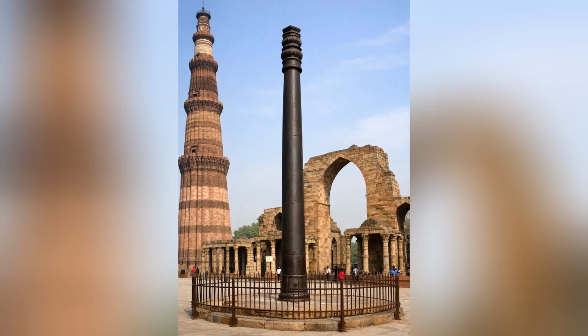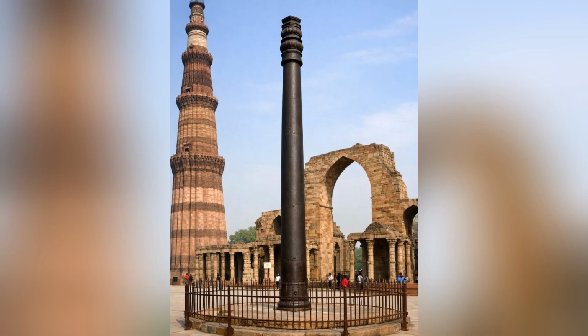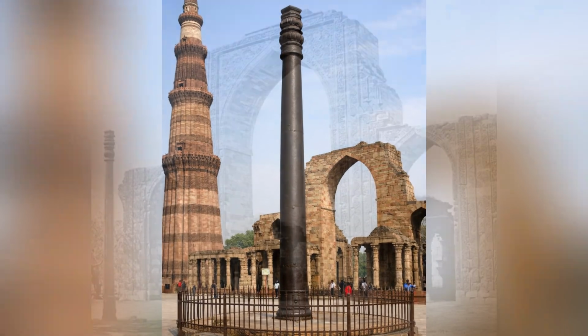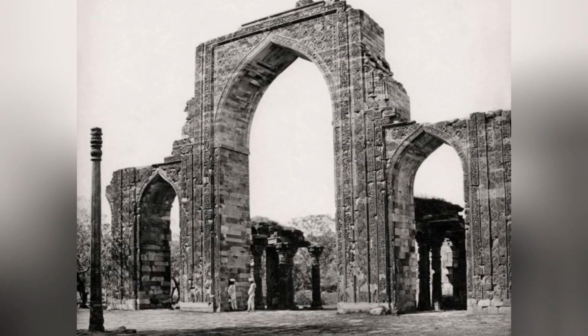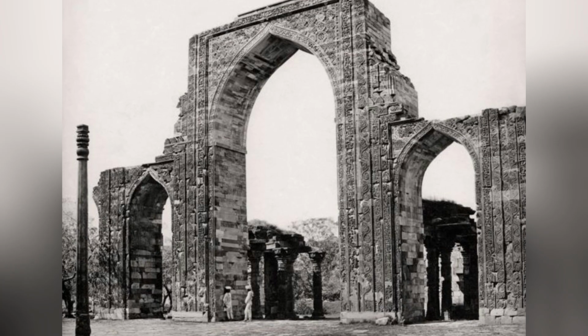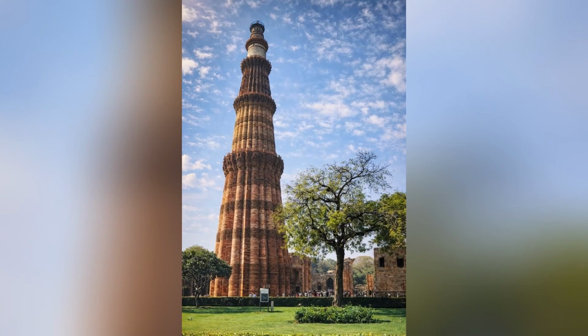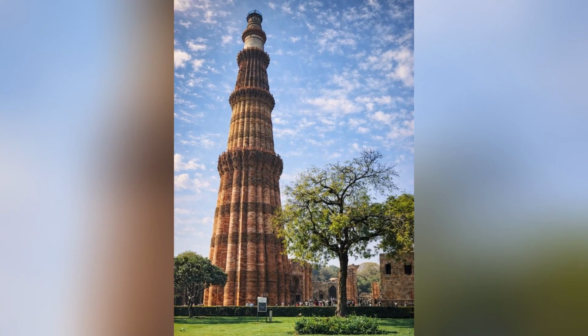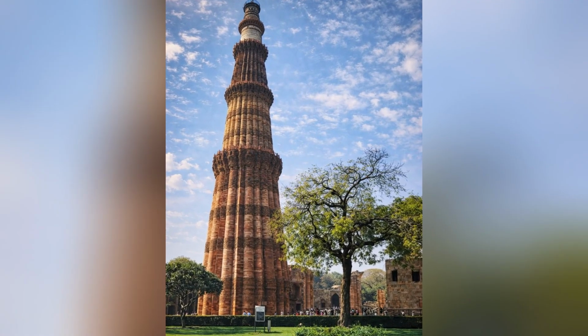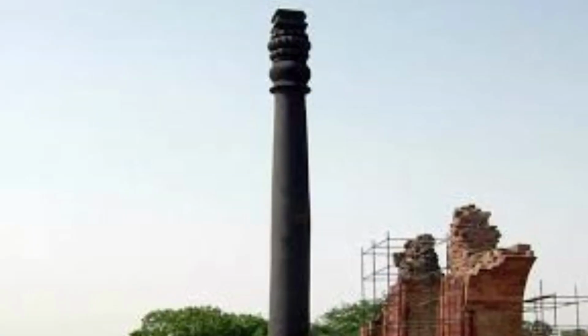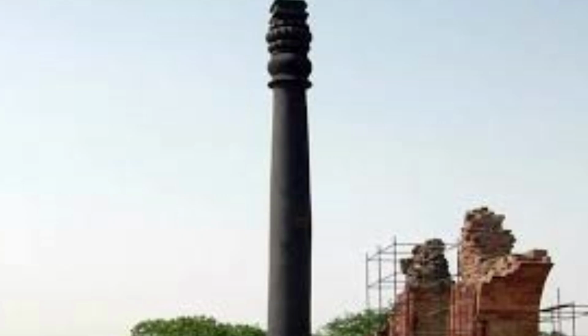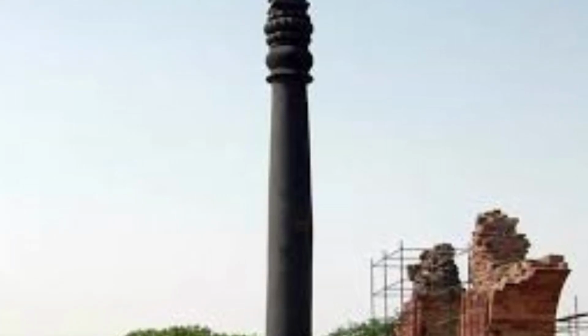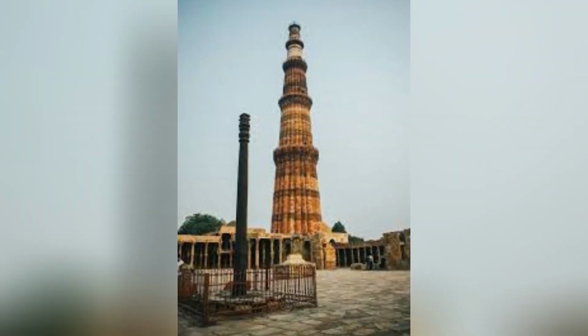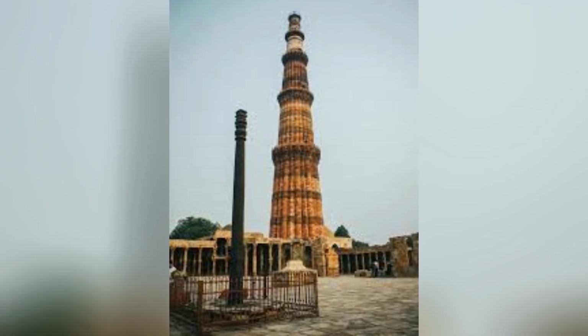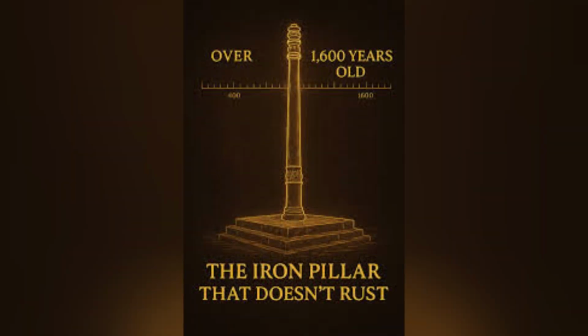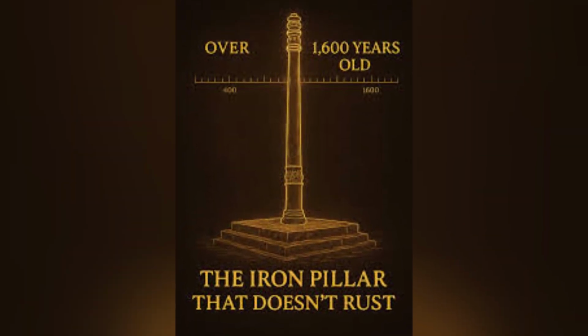The formation of the misawite film was a direct consequence of the high phosphorus content of the iron. The phosphorus, which was uniformly distributed throughout the iron as a result of the specific ore and the specific smelting conditions that were used, migrated to the surface of the iron as the initial stages of corrosion began, reacting with the iron oxide and the atmospheric moisture to form the iron hydrogen phosphate hydrate compound. The compound, once formed, sealed the surface of the iron, preventing further corrosion and initiating a process of self-healing in which any damage to the film was repaired by the continued migration of phosphorus from the bulk iron to the surface. The self-healing property of the misawite film is one of its most remarkable features, because it ensures that the protection is maintained even if the film is scratched, chipped, or otherwise damaged.